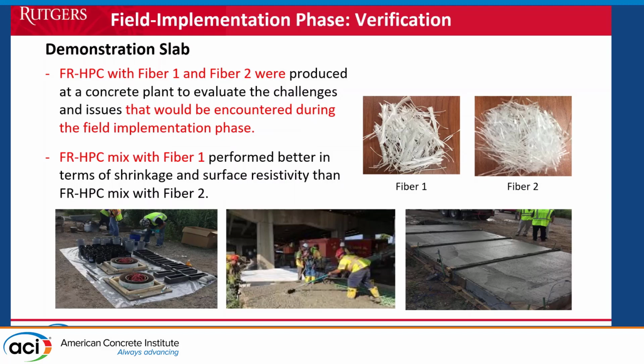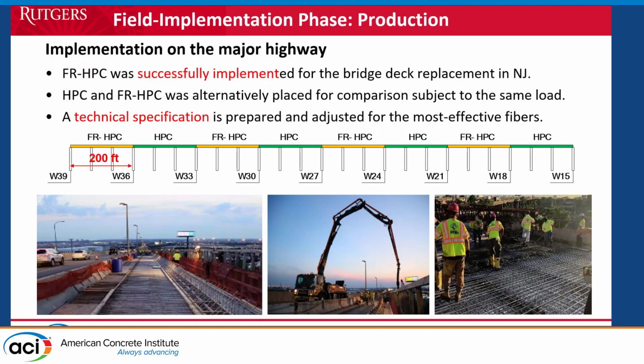And we did the same testing, same samples. We took them back to the lab. And once the demonstration solved all the technical logistics of pouring the concrete, we selected spans, each a continuous 3-span, about 200 to 225 feet. And we alternated the mixes with fiber reinforced high performance concrete and the high performance concrete mixes. And it was very well pumped.